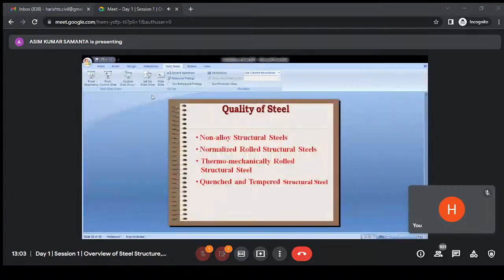Another is thermomechanically rolled structural steel. We know when steel is rolled, water is injected on it so that the thermomechanical treatment takes place. In this way, steel gets more strength, but weldability is reduced. Nowadays, thermomechanically treated rebar is very easily available for concrete structures. It is done for rebar just because rebar is not necessary to be welded. But if welding is a criterion, then we have to be cautious about using thermomechanically rolled structural steel. But if the members are joined with bolts only, then there is no problem using thermomechanically rolled structural steel.